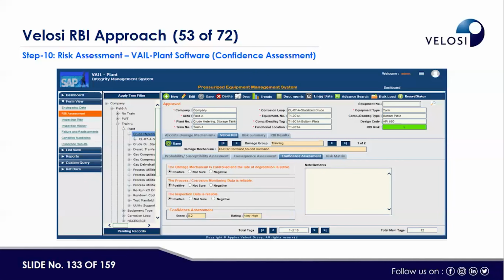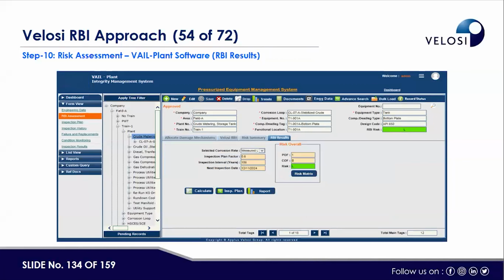From the risk assessment point of view, then we have to do inspection planning or the confidence in assessment. For example, if the damage mechanism is controllable and the rate of degradation is stable, the process corrosion monitoring data is reliable, or the inspection data is reliable. This is called inspection confidence assessment, and this also has an effect on the next inspection and the risk. So then we get the next inspection. The next inspection is this, and from the risk point of view this.